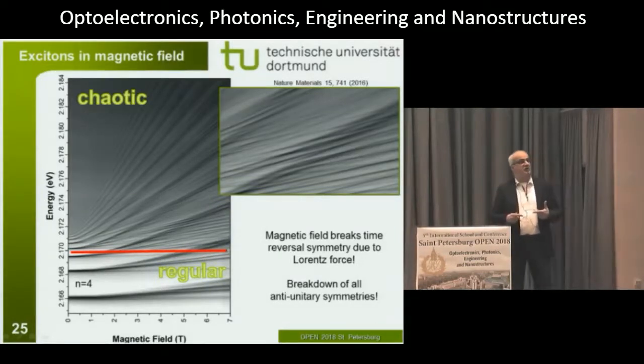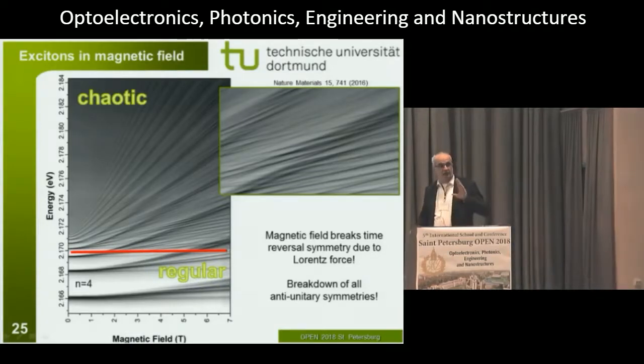You have a regular motion when you bring these two lines in resonance, for example, by varying the magnetic field, and when they cross each other, you still have regular motion. You are in the quantum chaos regime once you bring two levels in resonance and you find in all cases, really in all cases, anti-crossing. And this is exactly what we find here. So crossings are no longer observable, you have only anti-crossings.